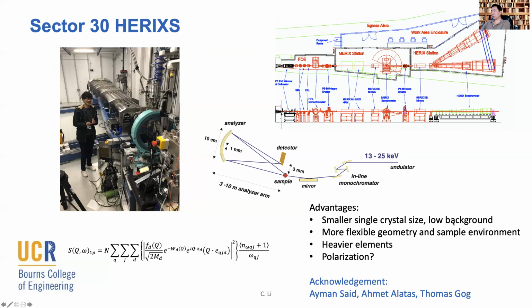And the sample environment allows us to work with higher pressure, which is one of the important benefits of X-ray scattering. We also have a different scattering intensity dependence on elements in comparison with neutron scattering. So that sometimes allows us to do combined neutron and X-ray work to decompose the contributions from different elements.